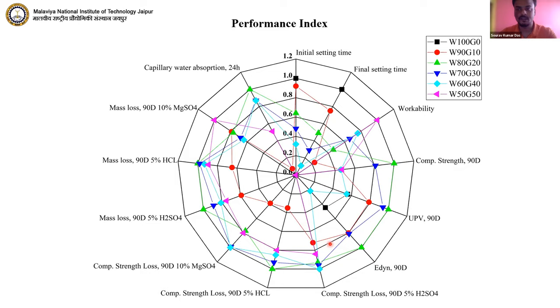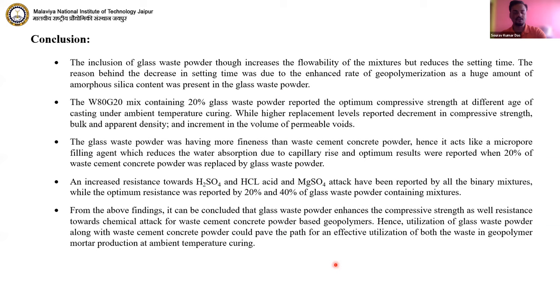And these are just the conclusions. From these conclusions, I can say that there is an increase in the flowability of the mixture along with reduced setting time if you incorporate glass waste, and the 20% and 40% glass waste powder mixtures are more resistive than other mixing proportions. And the last and most important point: from the above findings, it can be concluded that glass waste powder enhances the compressive strength as well as resistance towards chemical attack for waste cement concrete powder based geopolymers.